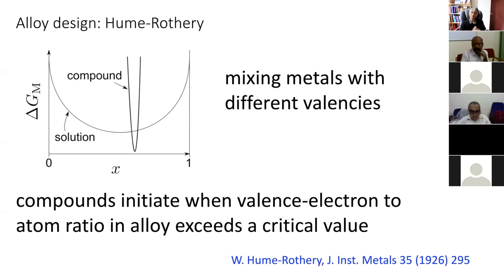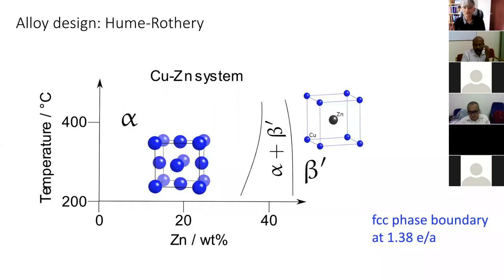So when we mix metals with different valencies, the electron to atom ratio will change as a function of concentration until it reaches some particular value where you trigger another phase. And the classic system that Hume-Rothery considered, he actually looked at very many systems, and his rules actually work for a large number of systems.